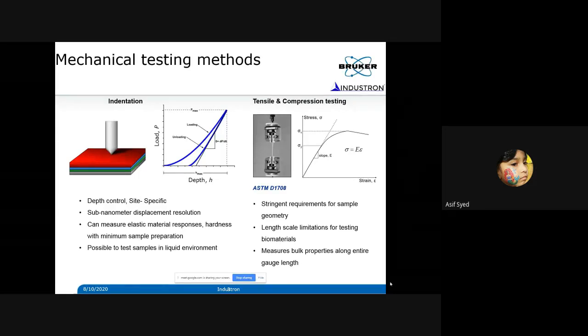Both of them apply forces and measure displacement, whereas in the indentation technique you are applying force through a sharp probe and measuring the displacement of the probe into the sample. Okay, the result is basically a load displacement curve, and from that you try to get the mechanical properties. That is what you're trying to do.